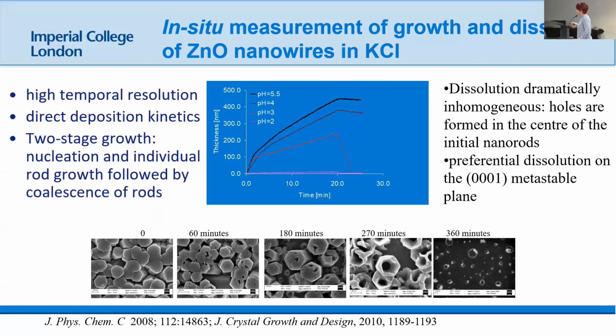And what we found throughout this was a two-stage growth phenomenon: rapid nucleation and then slower growth. And it's this second phase of growth that actually controls what you get. So we can do imaging at different points. And this here is where we turned off the potential, so we stopped generating hydroxide. You get a diffusion away of that and a reversion back to bulk conditions, and you can see at pH 2, it just redissolves. But at pH 4 and 5, you start to get these really interesting structures.